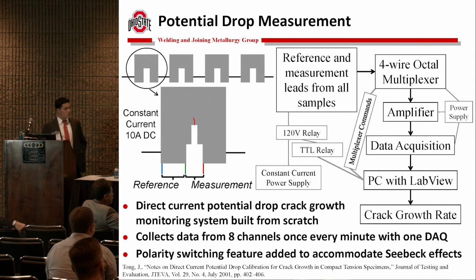The potential drop system looks like this if you're not familiar. So I have a current daisy chain through all these samples, and so you simply take a reference measurement, and this is actually determined to be one of the better locations to make your reference measurement. And so the actual crack growth measurement, of course, happens here, and you simply compare these voltages as you go. The basic principle is that you have a constant current power supply, which is this horizontal line, and so then all these leads, the reference and measurement leads from all the samples, go into a multiplexer, which basically, based on the program in LabVIEW, will select the channel and write the channel, and select the next channel. So then you only need one amplifier and one data acquisition unit.